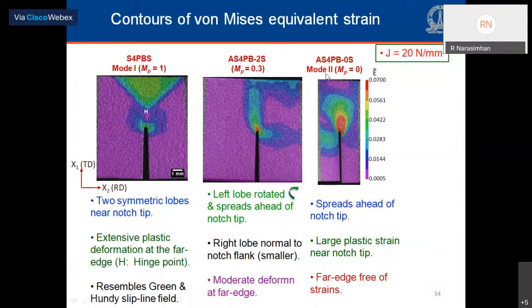In the mode 2 case, there's much less twinning at the far edge of the specimen as compared to the mode 1 case. And also strain is mostly focused around the notch tip.